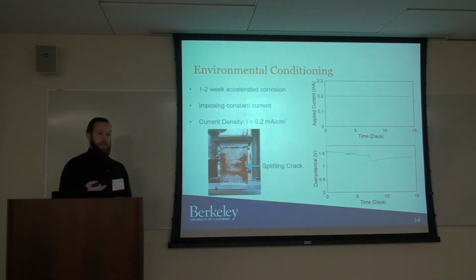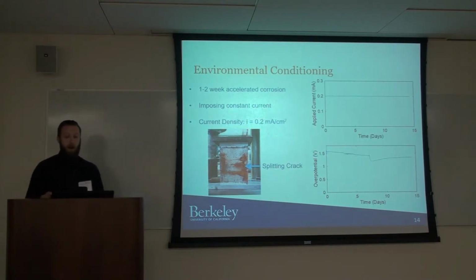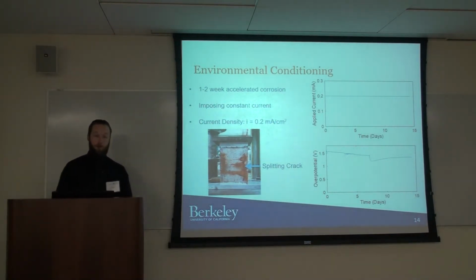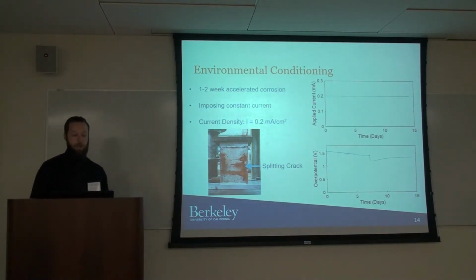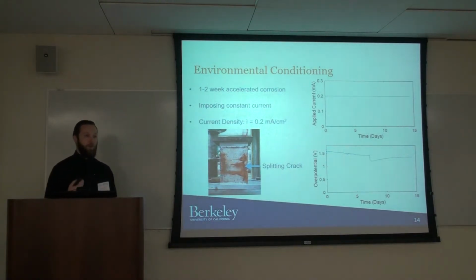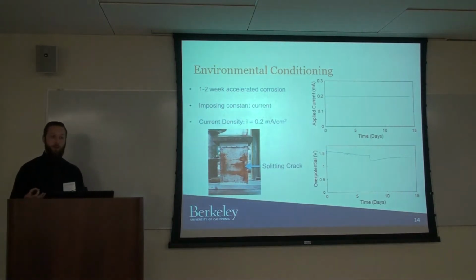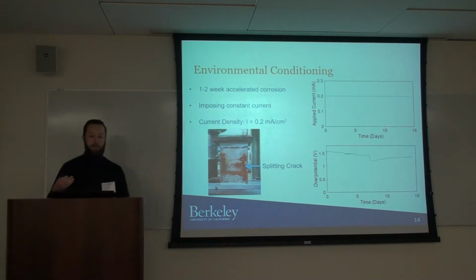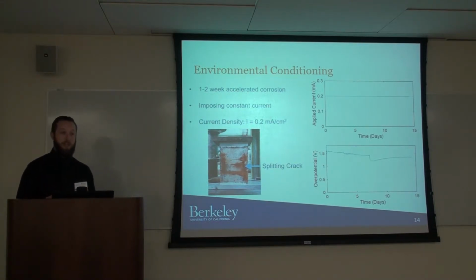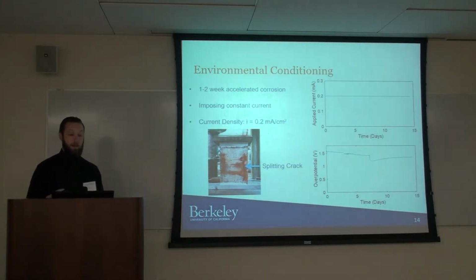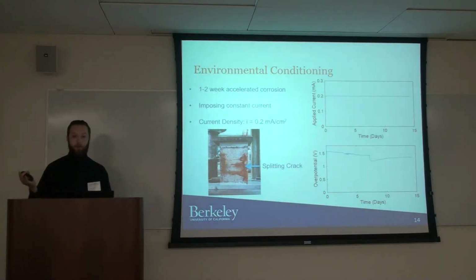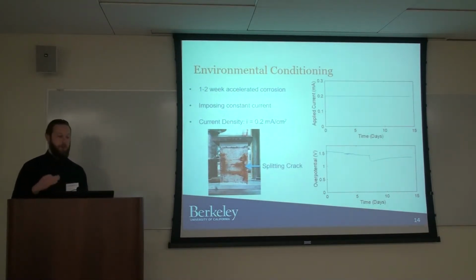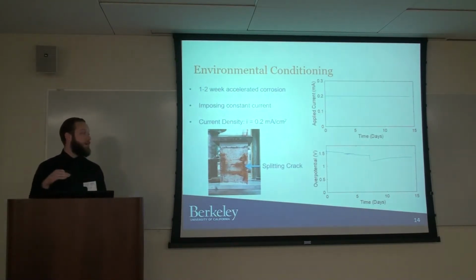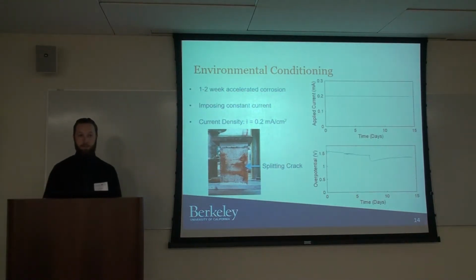So to look closely at the environmental conditioning, this is how we are applying corrosion damage to this specimen. We're immersing it in a saltwater bath, and then using a potentiostat to apply a constant current. And while we're doing that, we're measuring the potential, which you can see fluctuates here with the formation of cracking in the specimen.